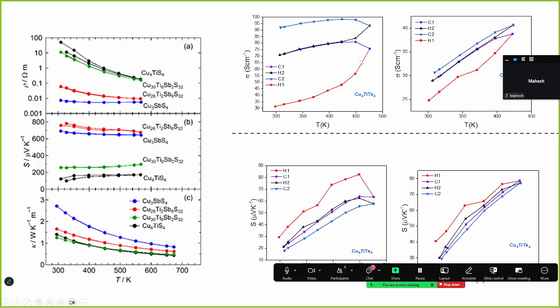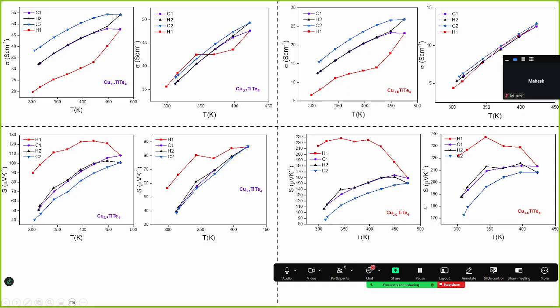Initially I took data at 200 degrees, then cycled, and it changes a lot. But if I go to 150 degrees, it comes up with the same data. So I'll just take 150 degrees from room temperature and do cycling. I think it's okay, right, Mahesh? Yeah, we discussed.